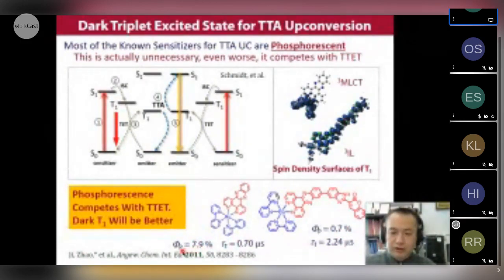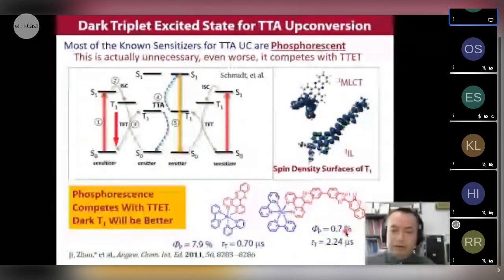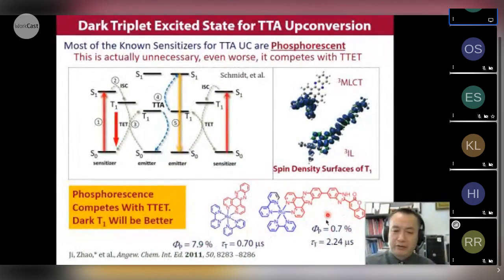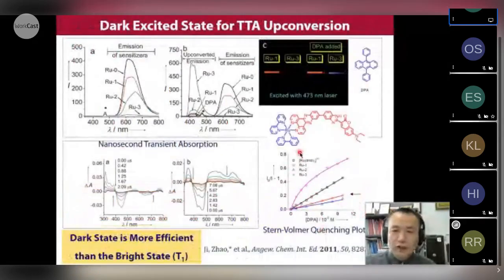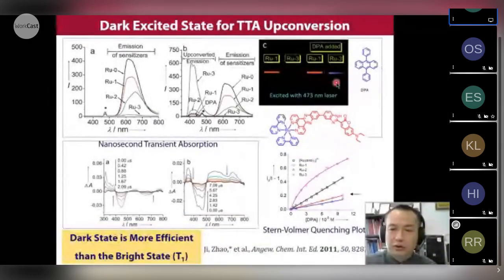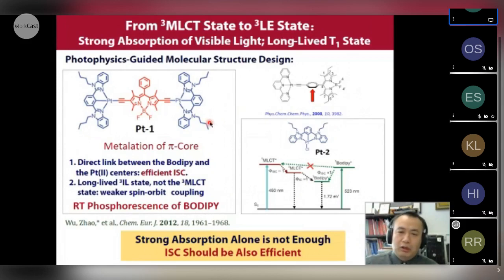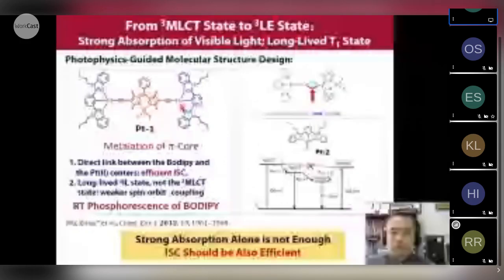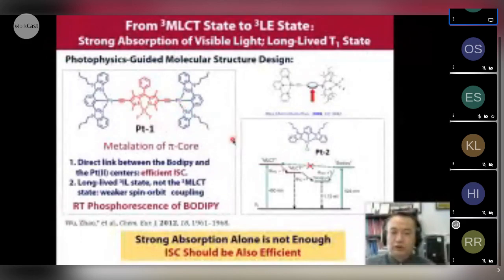So we reduced the emission efficiency to less than 1% from 8%. So basically this complex is with a dark T1 state. And we confirmed with the dark T1 state, actually we can have a stronger upconversion because we can have more efficient intermolecular energy transfer with the longer triplet lifetime. So next example, I will show how to design a new triplet photosensitizer with long lifetime intersystem crossing.